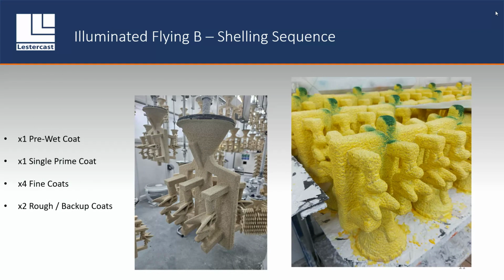Martyn's mentioned the shelling side of things. For those of you that aren't so familiar with the investment casting process, for this particular part, we have what we call a pre-wet coat, a single prime coat. Arguably one of the most important layers of the shell is the one that's in contact with the metal. Once you've got a really good fine coat, with no bubbles and really good definition, it has to dry properly as well. So we have some techniques to allow the shell to dry, checking temperatures inside the drying as well to make sure all the moisture's been removed, to make sure that first layer is absolutely dry before we apply the next coat.